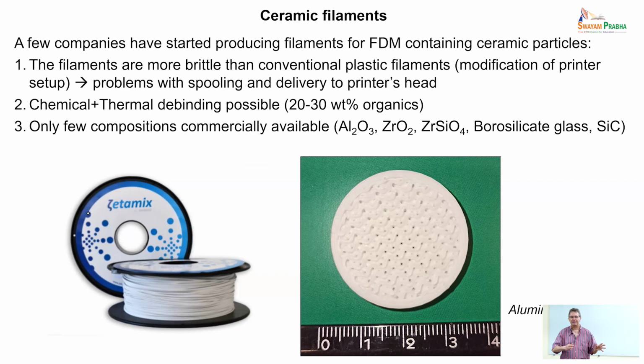And right now, you have to use acetone, which is, from the industrial point of view, not the best. But I guess they are transitioning towards trying to use water-based, water-soluble polymers. But the main point is that after you shape your ceramic material using this approach, you have about 30% organics, which is a lot in volume because, you know, zirconia is 5.5 grams per cubic centimeter, polymer is 1. Okay, so 30% organics means 50 volume percent organics. So you have a lot of organics that need to be decomposed.